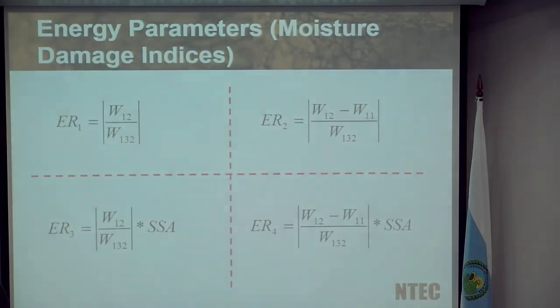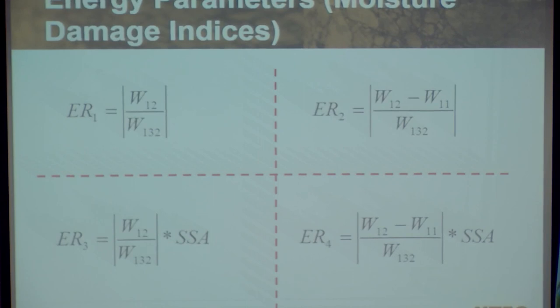And the bottom two equations are introducing what I've talked about previously, when I said the thing that we need to always remember is that if we can increase the specific surface area, in other words, the amount of surface area that our aggregates have that allows them to bond with bitumen, that has to be a good thing. So having materials that are relatively rough in terms of their surface area has to be good. And again, we can modify our energy ratios to take that into account by multiplying the top two ratios, the top two equations, by the specific surface area of our individual aggregate particles.